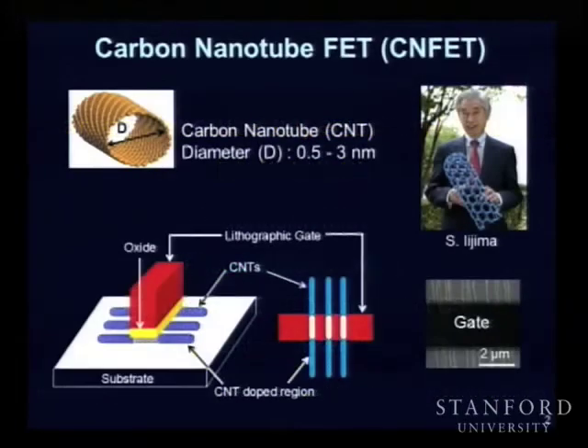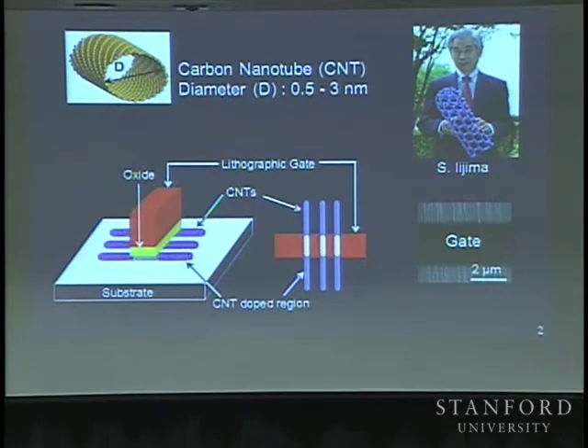Okay. So carbon nanotubes are rolled up cylinders of graphene with some amazing electrical properties. Carbon nanotubes, Iijima Sensei from Japan, he has a lot to do with these carbon nanotubes. He found them. And these cylinders of graphene, as shown in this cartoon, you would see a typical diameter between 0.5 through 3 nanometers. The carbon nanotubes that we grow in the CIS building right across the street, our diameters are somewhere around 1.2 to 1.5 nanometers.